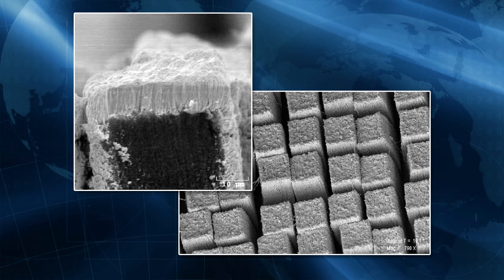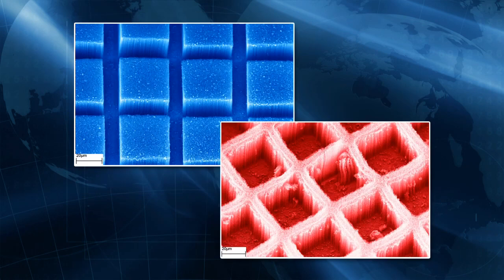And we're looking at some pictures that you sent us. These look like tiny cubes. Yes, if you zoom right in, the carbon nanotubes are very vine-like, and so we try to coat those with our photoabsorber materials. We've done it in the past using cadmium telluride as the photon-absorbing material. This proposal is using a new photochemistry known as CZTS, copper zinc tin sulfide.